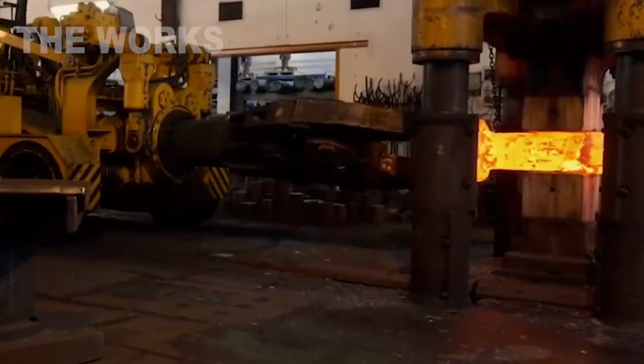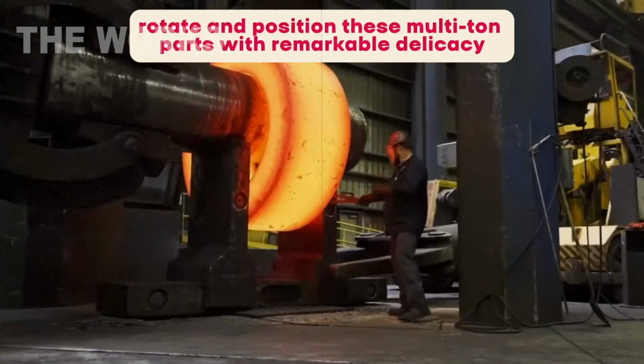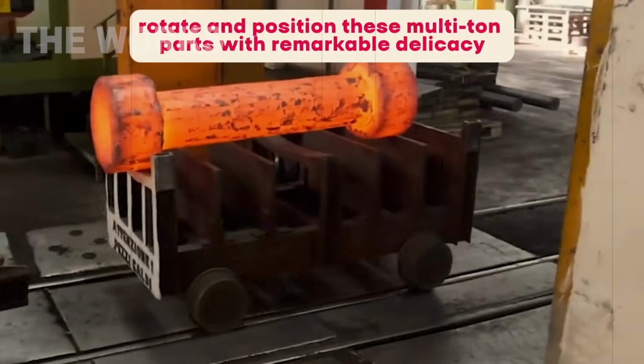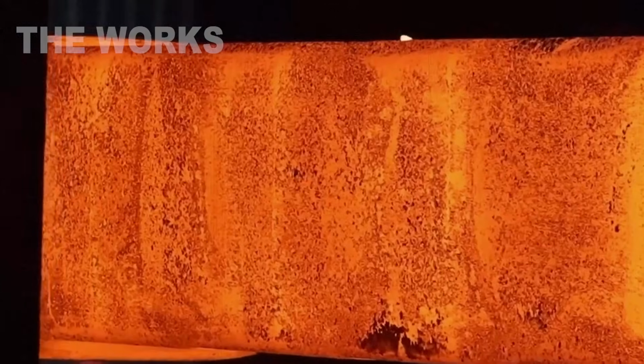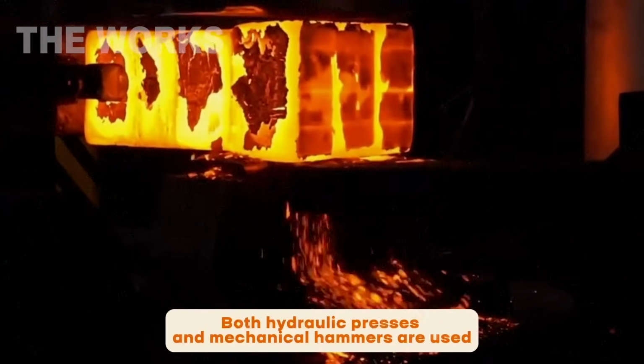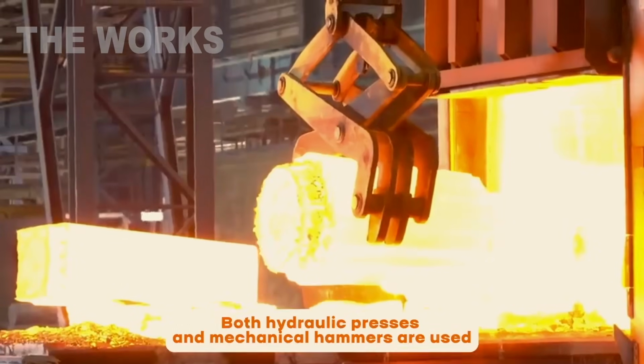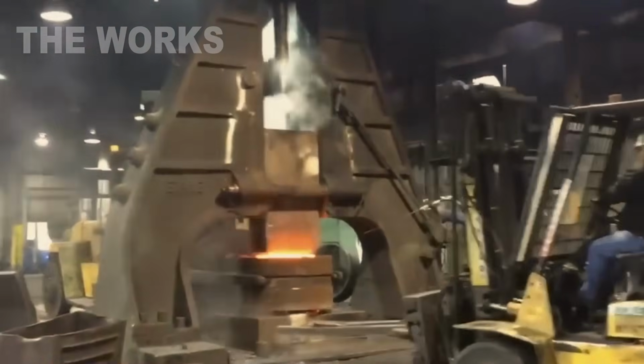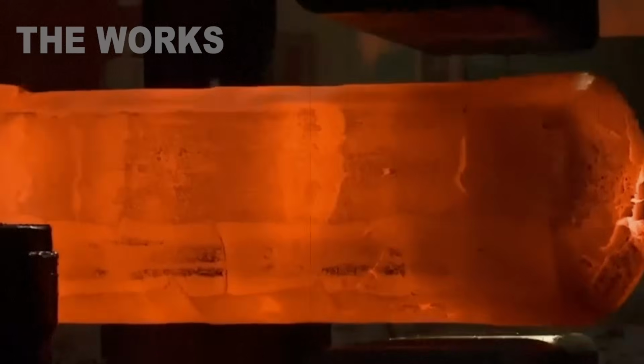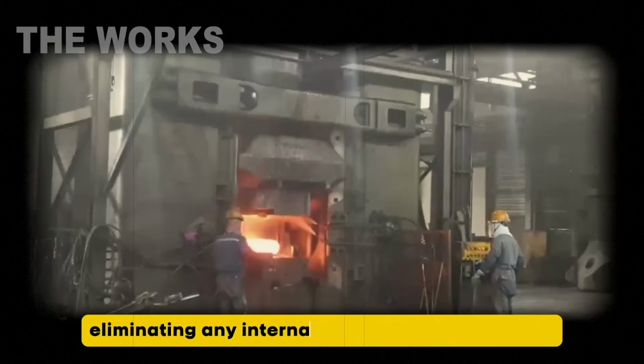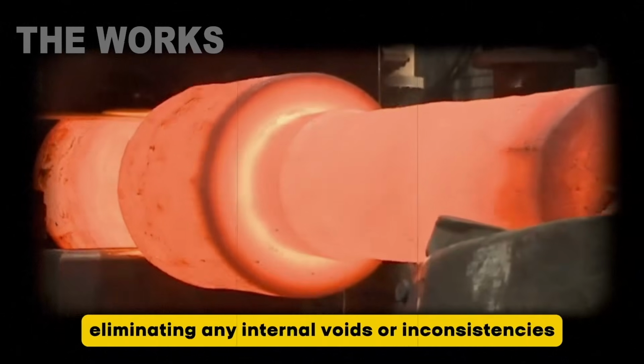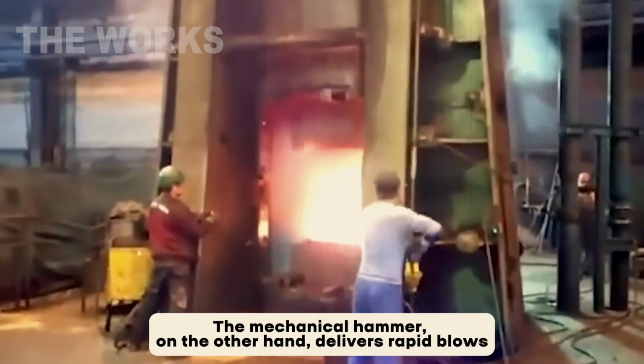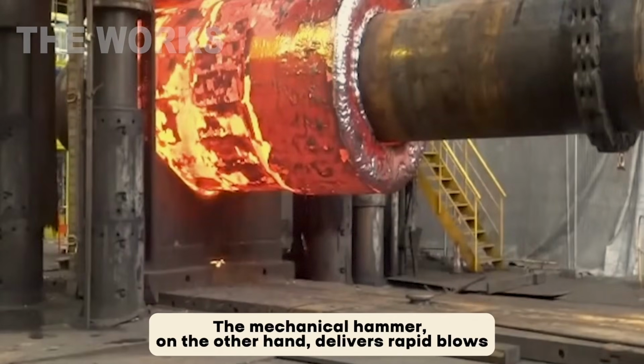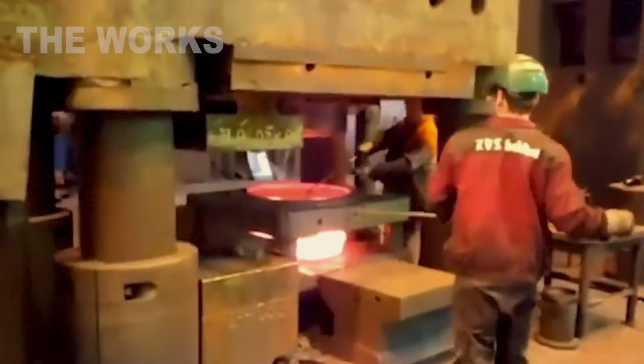Both hydraulic presses and mechanical hammers are used, depending on what the job demands. A hydraulic press applies slow, steady pressure, ideal for ensuring the force penetrates deep into the heart of the piece, eliminating any internal voids or inconsistencies. The mechanical hammer, on the other hand, delivers rapid blows that shape the surface and create specific forms. The forge master, a craftsman whose skills require decades to develop, orchestrates this symphony of heat and pressure. Between each strike or pressing, the piece rotates, gets repositioned, and sometimes reheated.